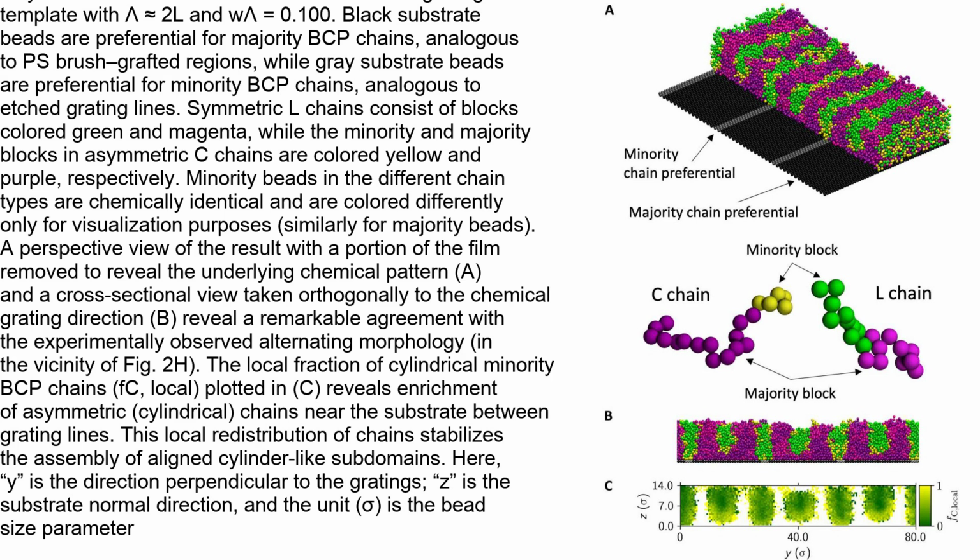The authors of this scientific paper discuss the characterization of complex three-dimensional morphologies that emerge through self-assembly of block copolymer blend thin films in response to underlying chemical pattern templates. They use synchrotron X-ray scattering to map a combinatorial sample, expanding the parameter space and providing morphology descriptors without human intervention. The autonomously derived results guide electron microscopy characterization, revealing previously unknown morphologies and helping to distill general principles of subdomain partitioning for predicting and designing patterns.